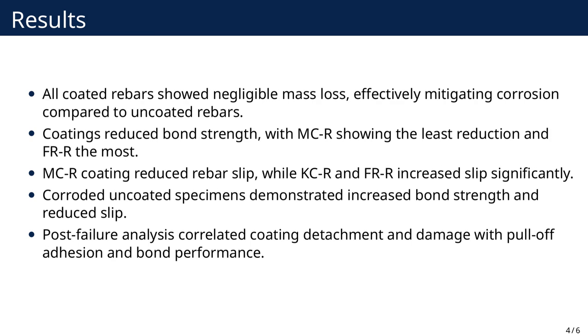Accelerated corrosion tests showed that uncoated rebars experienced a mass loss of 3.793, while all coated rebars exhibited negligible mass loss, indicating the effectiveness of the coatings in corrosion mitigation. However, coatings reduced bond strength. KCR showed a 16.3 reduction, FRR a 48 reduction, and MCR the least reduction at 9.4 compared to uncoated specimens.